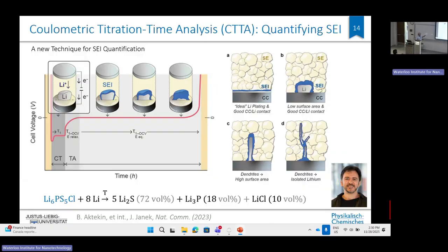So he said, okay, I have a lithium anode here. This is my source of lithium, and here's my current collector, and I play the game of a reservoir-free cell. So I plate lithium here. If my electrolyte is stable, the lithium will stay and stay and stay and will not react away. If my electrolyte reacts, there will form an SEI. It will consume the lithium over time until the lithium is gone. So this is cell voltage, this is time. I plate lithium here, then I let it relax, and then I wait. And as long as there is lithium here and lithium here, the cell voltage is 0 volt.